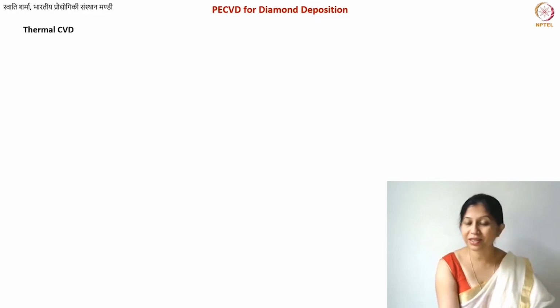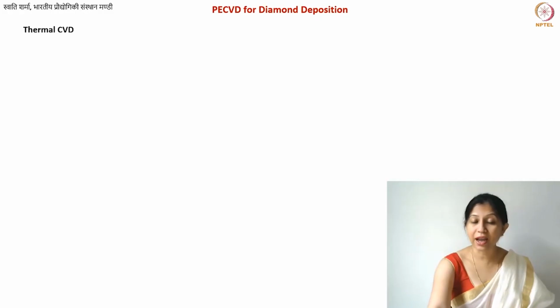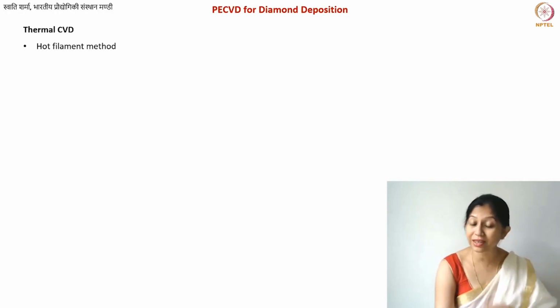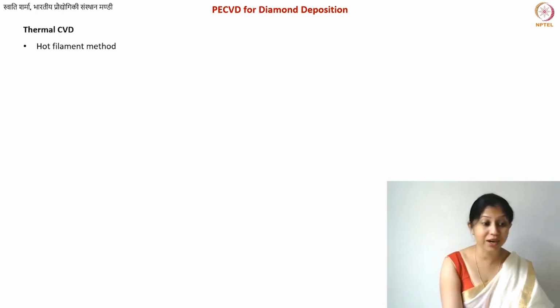So this is also in a way a plasma enhanced CVD, but here the reactive hydrogen species that you're getting, and also some argon gas or whatever is your carrier gas, is also getting ionized, but all of this is happening because of very high temperature. For the hydrogen species, you know already that you need to go above 2000 degrees centigrade for getting the atomic hydrogen. So definitely this method requires temperatures above 2000 degrees centigrade.